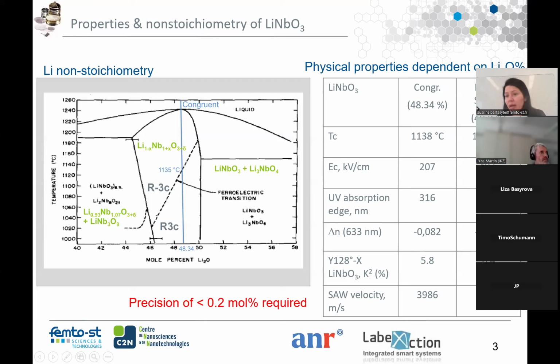Then we see that the refractive index or birefringence is changing, electromechanical coupling changes, so velocity is changing, so acoustic velocity is changing. So basically, if we want to bring this material to acoustic filter application, where your frequency has to be precisely controlled, we need a precision in composition of 0.2 mol percent in lithium to be reproducible, and we need control at this level. For single crystals of lithium niobate in photonic applications, we require a precision of 0.1 mol percent. So it means we need to be very precise.